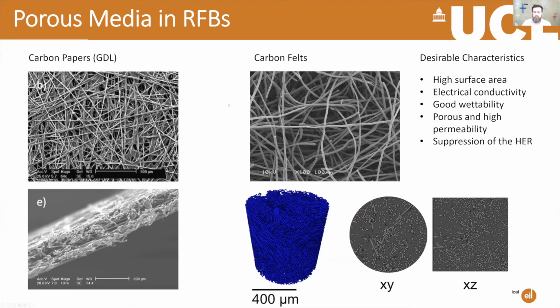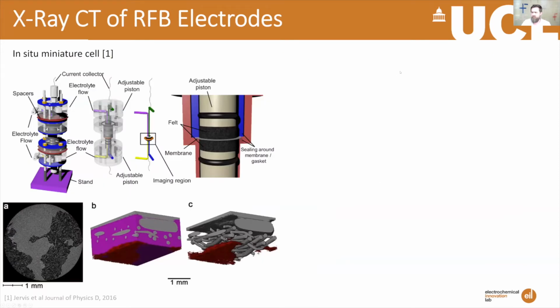So there's a lot of work going on to try and find things that will catalyze the vanadium reaction, but not cause hydrogen evolution. So we've used X-ray CT to study these materials. They're sort of ideal, they're porous, they're about the right length scale for what X-ray CT can study. And we've done it in a variety of ways.